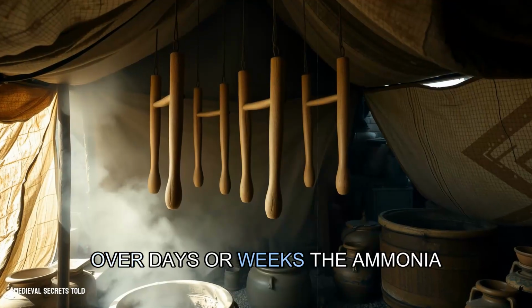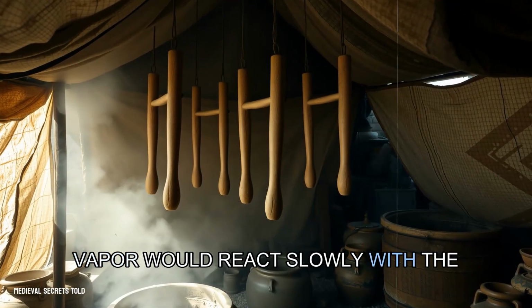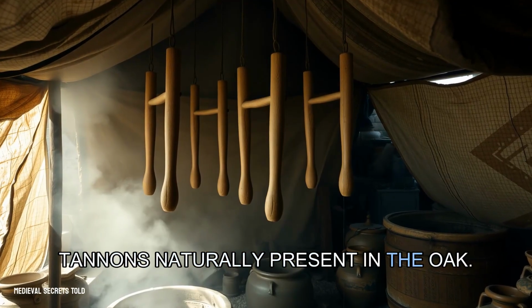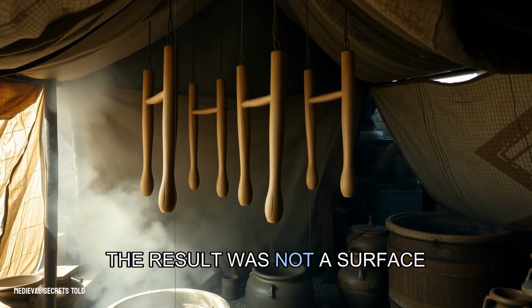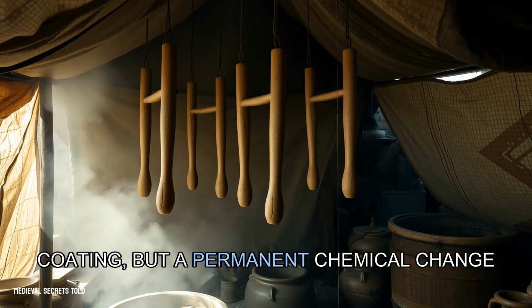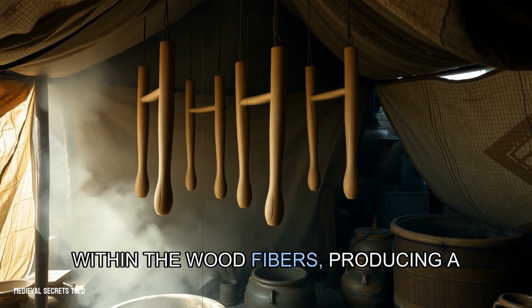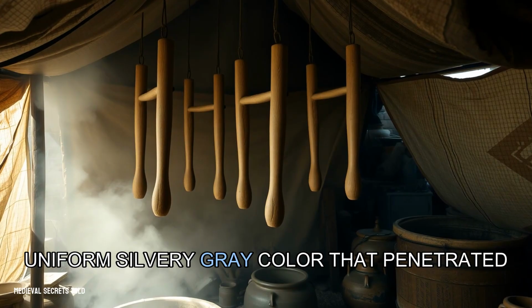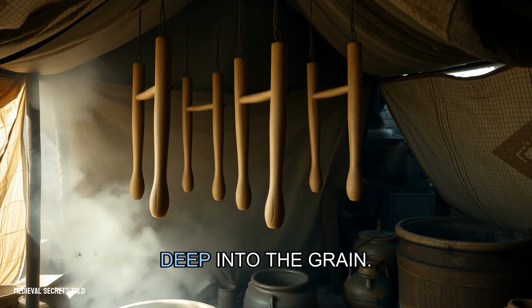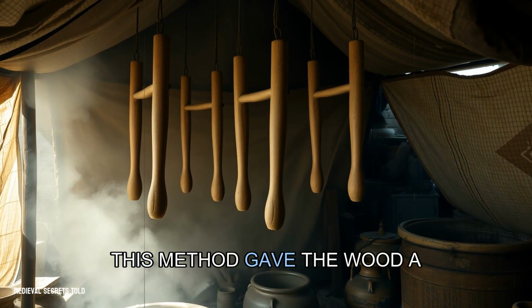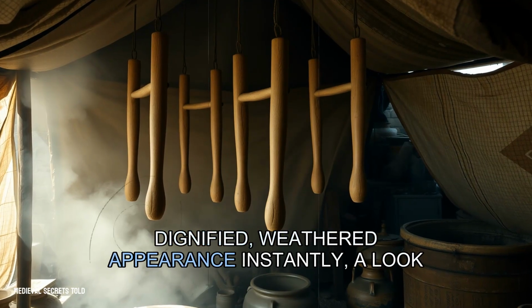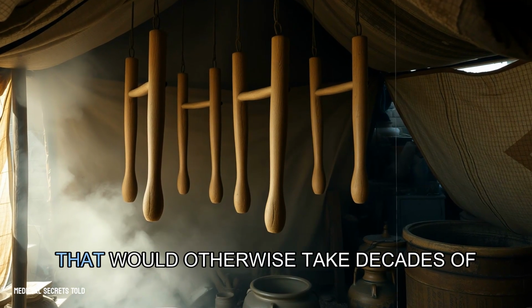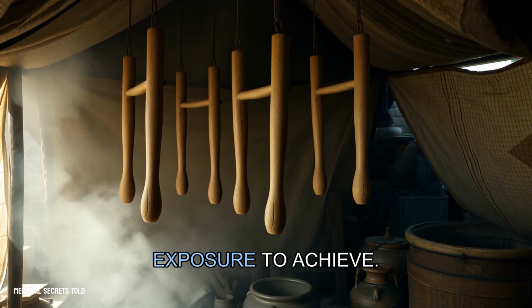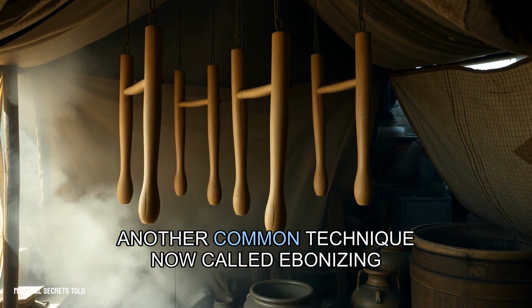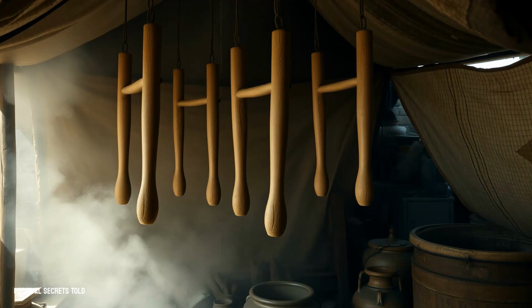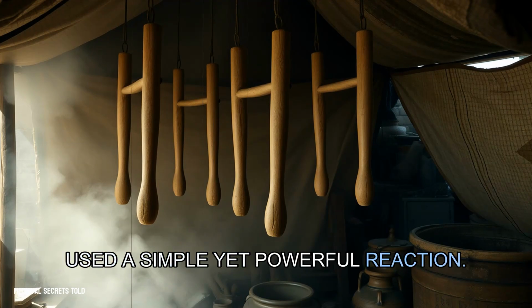Over days or weeks, the ammonia vapor would react slowly with the tannins naturally present in the oak. The result was not a surface coating, but a permanent chemical change within the wood fibers, producing a uniform, silvery gray color that penetrated deep into the grain. This method gave the wood a dignified, weathered appearance instantly, a look that would otherwise take decades of exposure to achieve. Another common technique, now called ebonizing, used a simple yet powerful reaction.